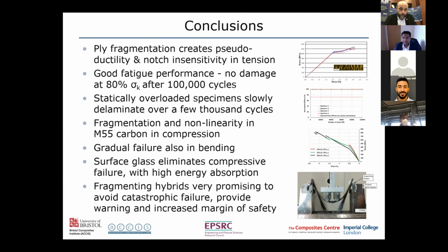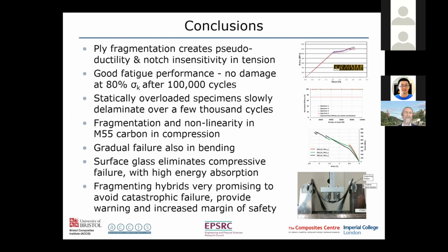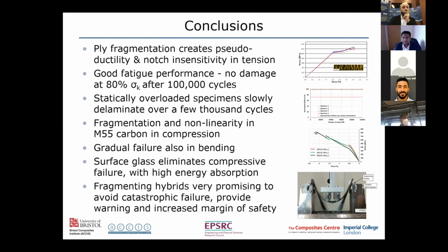And I suppose you could consider it a sort of size effect, but what it's really about is the way that the carbon fails by a critical cluster of broken fibers. When you have a hybrid with very thin plies, it's very difficult to form that critical cluster because you don't have enough fibers. And if you do have a weak fiber, it's probably only got 2 fibers through the thickness. So it has to form a cluster in the side directions only, not in the through thickness directions. So you inhibit the ability to form a critical cluster, and the failure strains are very substantially increased.